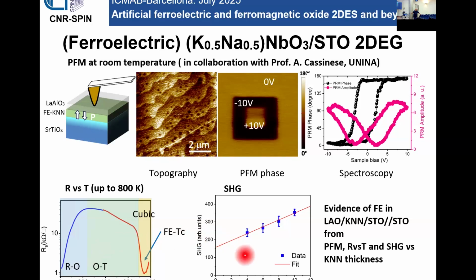Then our colleague Andrea Rubano performed some second harmonic generation measurements, which suggest that there is at least a component of the second harmonic generation signal. A second harmonic generation signal is present when you have a non-centrosymmetric material or there is a breaking of symmetry. There is at least a contribution from non-centrosymmetric KNN because the signal increases with the KNN thickness. This means that the KNN is clearly non-centrosymmetric, which is a condition to have ferroelectricity.